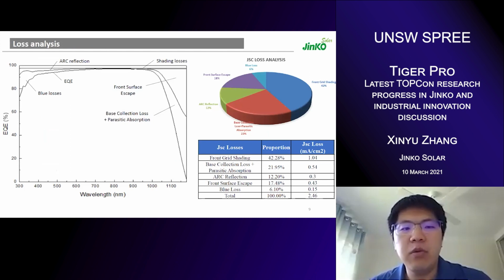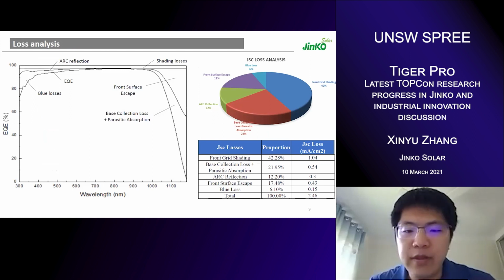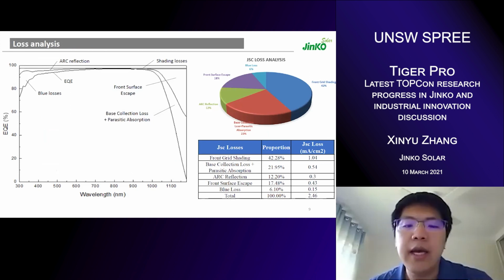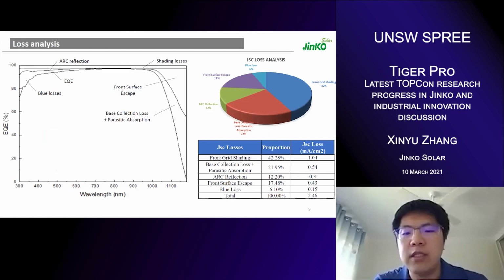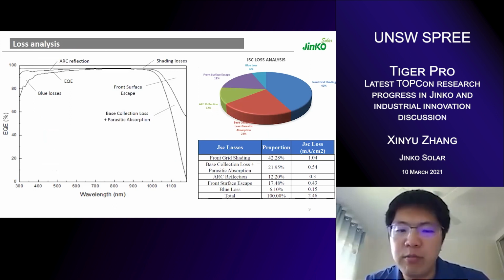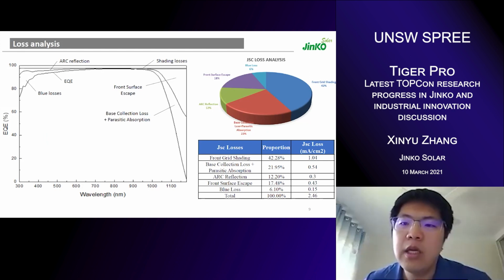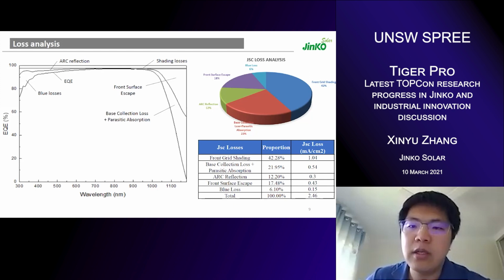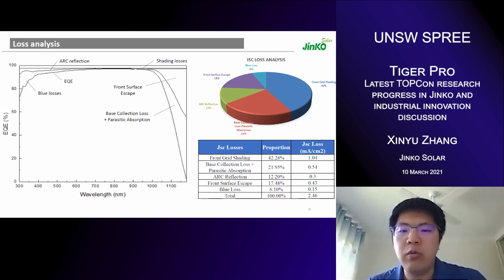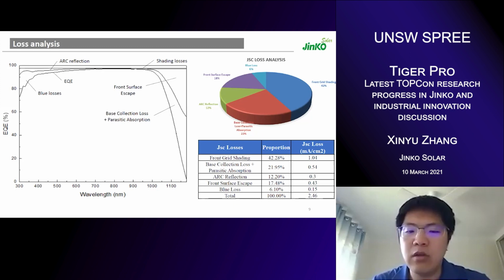Well, in terms of the loss analysis, we have done very detailed loss analysis, including some calculations for the champion cell batch, and we can see that the major power loss is still at the front grid shading. It's challenging to further improve the front grid shading, but also it's possible. With the idea of reducing the metal coverage areas and further better optical control, we do have confidence that we can improve the light absorption and reduce this power loss significantly. So this is a good analysis and also good news.